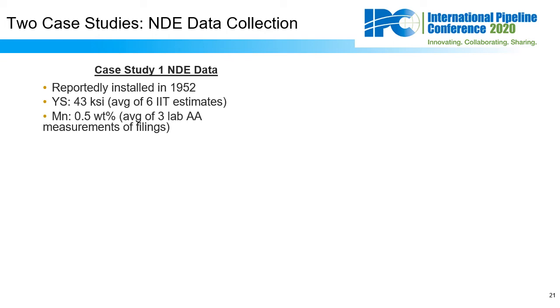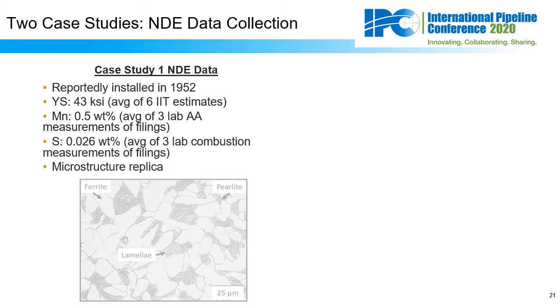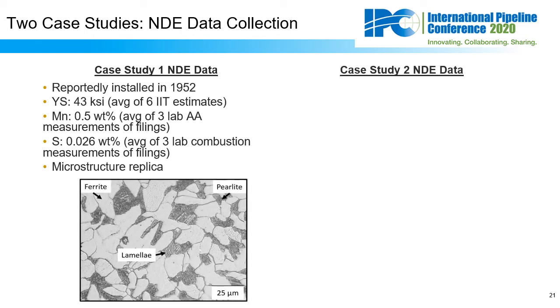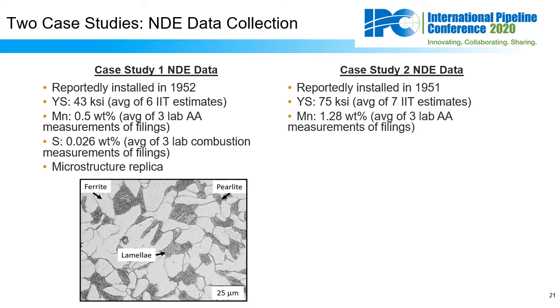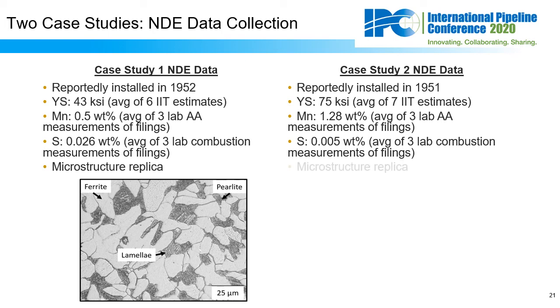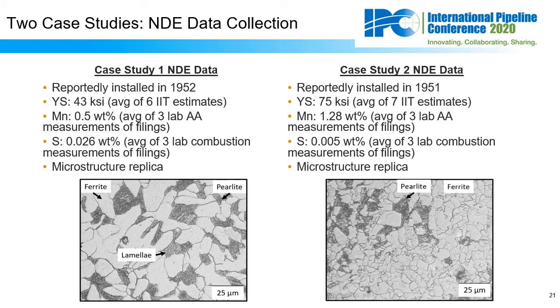The first of our two case studies is for a line pipe that was reportedly installed in 1952, and the NDE data provided an estimate of about 43 KSI yield strength, a manganese content of 0.5 weight percent, sulfur of 0.026 weight percent, and the microstructural replica shown here. The second case study was reportedly installed in 1951, but the NDE data provided an estimate of 75 KSI yield strength, manganese content of 1.28 weight percent, sulfur of 0.005 weight percent, and this microstructural replica.